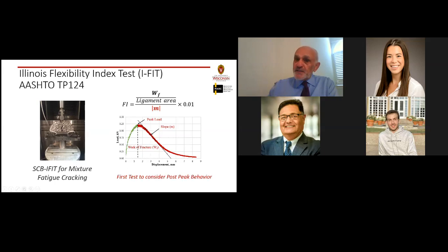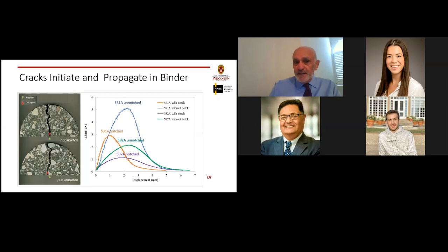That post-peak slope is so important for testing our hypothesis that we need large strain, because that's what the large strain in the mixture actually is. Here you can see the pictures of how the cracking is propagating. The importance of this picture is to see where the crack is propagating. There is certainly evidence that most of the cracking is happening in the binder, and therefore these binders are stretched to very high strain before they fail.